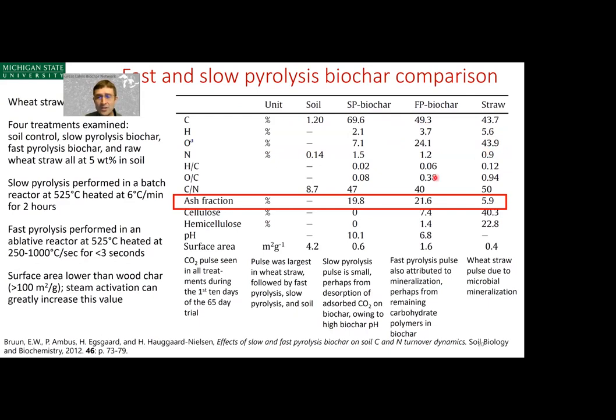The ash fractions are about 20% for slow pyrolysis and almost 22% for fast pyrolysis. So they're not too different from each other, but they are quite different from the original wheat straw. That's because the biochar concentrates the inorganic fraction of wheat straw into itself. The inorganics typically aren't volatile, so during pyrolysis, they just become a fraction of the biochar.